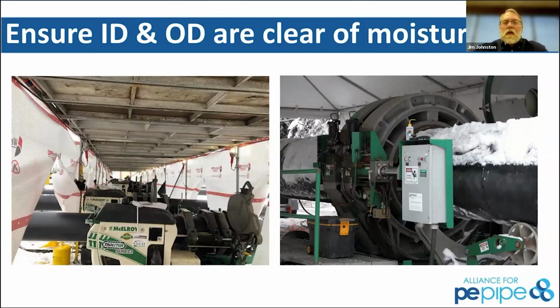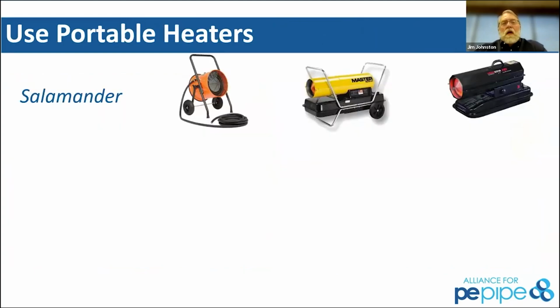It's a simple process. Just clean it off before you put it into the machine and make sure that you've got good, clean capabilities. So use portable heaters, and there are a ton of choices out there. And Chris, you might talk about some of them that you've seen out in the field. We want to make sure that you're using indirect heat. If you're using a flamed heater, you don't want to put flame on polyethylene. But salamanders are one of those big ones that we see used quite a bit, and you can use indirect heat off of that through a venting system or a tube to run over into the pipe or onto the pipe or into the tent to maintain that temperature and raise the temperature inside the heating zone.